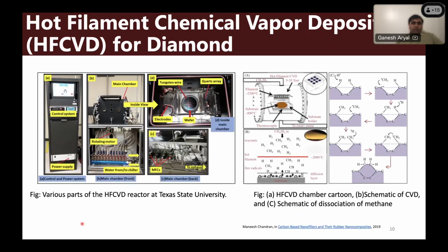So now, how do we grow the diamond? We grow the diamond using hot filament chemical vapor deposition. These are the various parts of the hot filament chemical vapor deposition reactor in our lab. The chemical reaction is based on the dissociation of methane at high temperature, so the hydrogen starts to dissociate from methane, and we get carbon at a very high temperature, around 800 degrees Celsius. When methane detaches, it separates into carbon and hydrogen, and the carbon is deposited on the substrate.